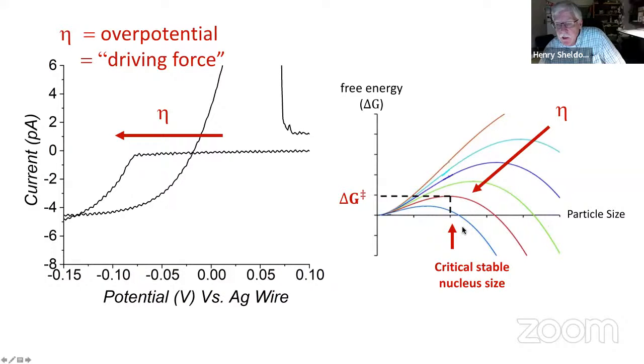What I mean here is, let's look at the red curve right here. You can nucleate a particle, and it can be growing, and you've got to get to this maximum. And once you reach the maximum, then it's all downhill. The particle is stable. So you've got to grow the particle to this critical size before it's stable. If I'm scanning along the blue curve at low overpotentials, I'm creating particles all along this curve, but they're not stable, so they just dissolve. So as I'm moving along here, I'm actually getting particles forming, but they're unstable and they dissolve.